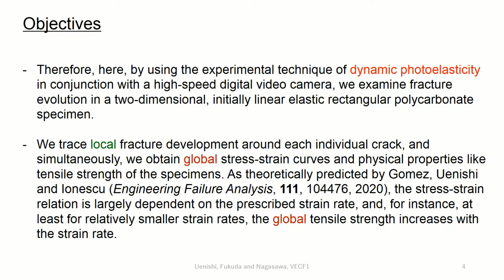Therefore, here, by using the experimental technique of dynamic photoelasticity in conjunction with a high-speed digital video camera, we examine fracture evolution in a two-dimensional, initially linear elastic rectangular polycarbonate specimen where sets of cracks are prepared by a digitally controlled laser cutter and tensile strain with a prescribed constant rate is externally applied. We trace local fracture development around each individual crack, and simultaneously, we obtain global stress-strain curves and physical properties like tensile strength of the specimens.